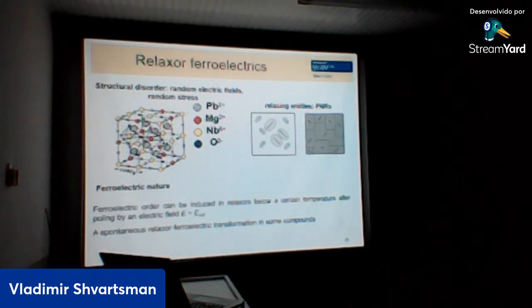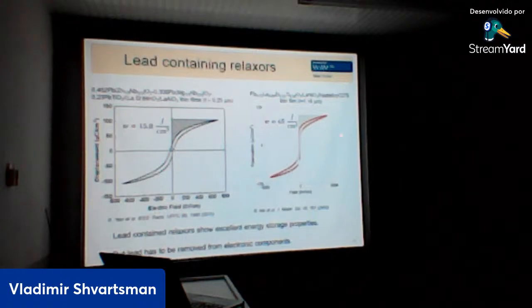And third, these relaxors are pretty close in energy to the classical ferroelectrics, and in principle, ferroelectric order can be induced in these materials below a certain temperature by a high enough electric field which exceeds a critical threshold. And in some materials, we can even observe a spontaneous transition from the relaxor to the ferroelectric state. One example of a relaxor is, as I said, PMN. We can introduce also zinc, which is also divalent but has a different size from magnesium. And so we have disorder.